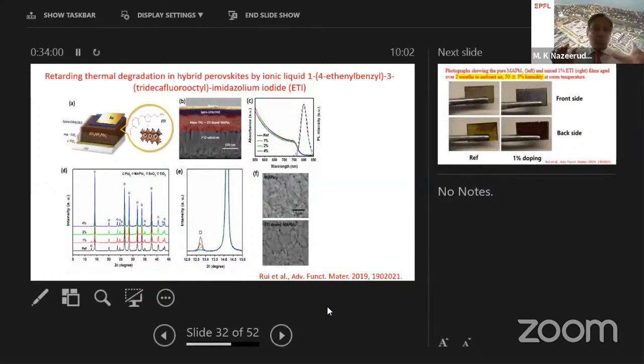So instead of doping pure ionic liquid, can we functionalize so that this material can act as a functionalized ionic liquid? The cell configuration is shown on the B panel. This is similar to our previous configuration, NIP, followed by the spectral properties shown here. There is not a big difference when we are using 1%, 2%, or 4% ionic liquid. The spectral properties remain the same.